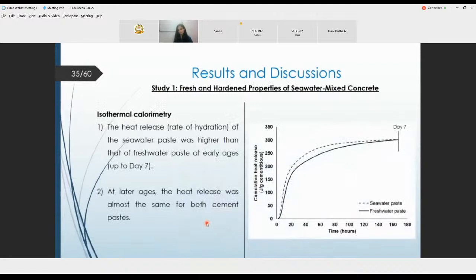As for the isothermal calorimetry, the heat released and the rate of hydration of the seawater paste was higher than that of freshwater paste at early ages, up to 7 days, as seen here. At late ages, the heat release was almost the same for both cement pastes.